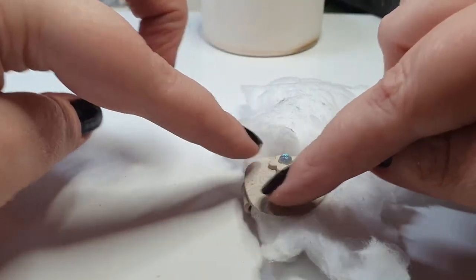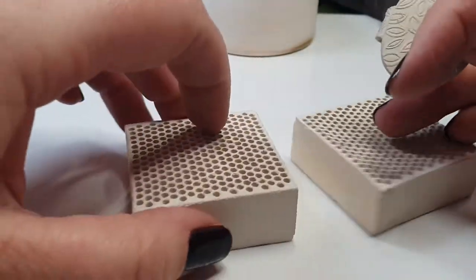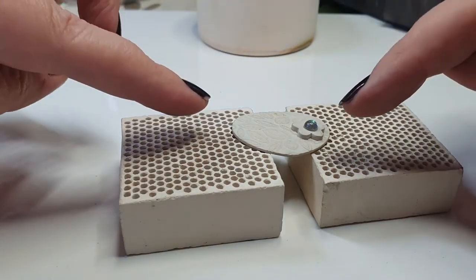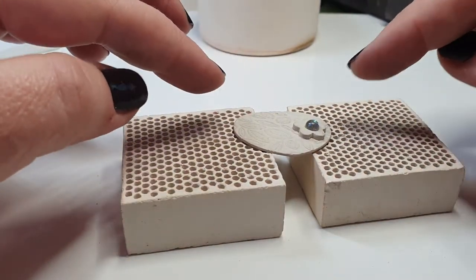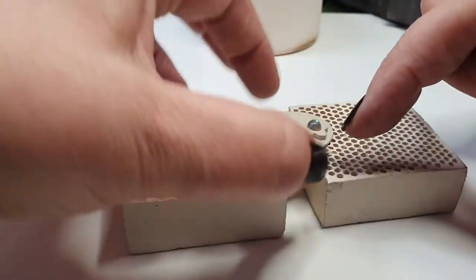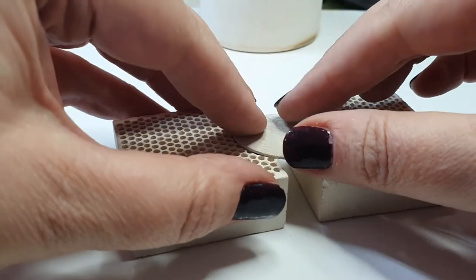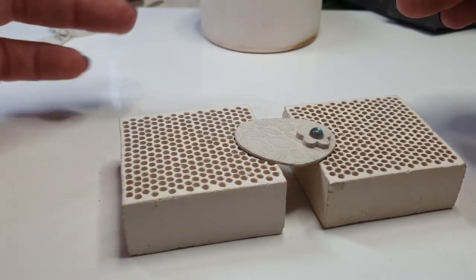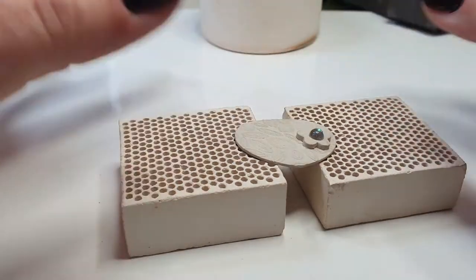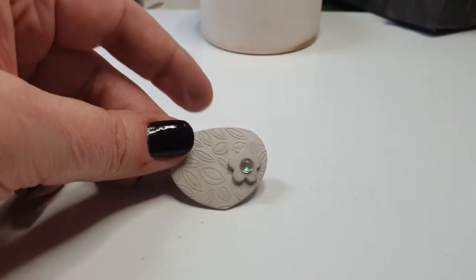The easiest way I like to do it is with these firing blocks. You simply set the pendant between two blocks like so and fire it that way. This also works for things with ring toppers — you can lay the ring on its side with the top lying off the end. That works well for something like a bezel cup, but if you have a really weighty top, I wouldn't do it that way; instead, fire it in vermiculite standing on its end.